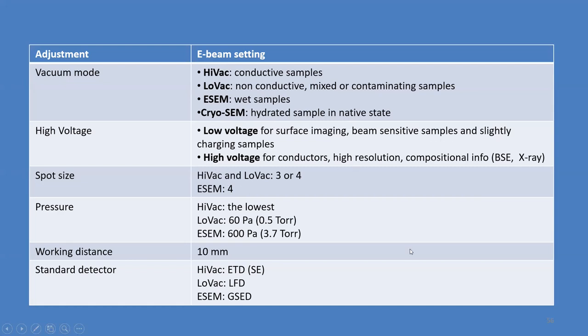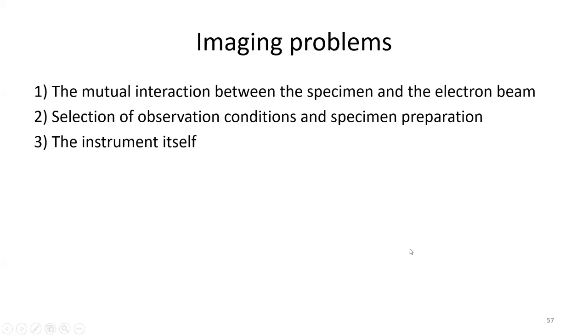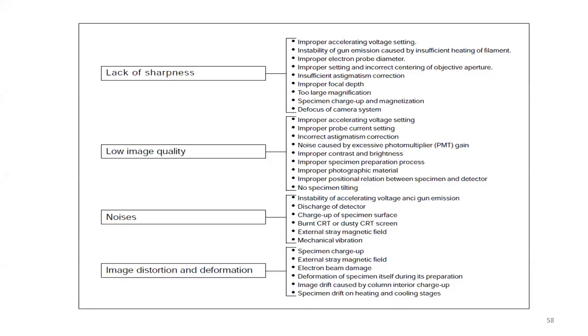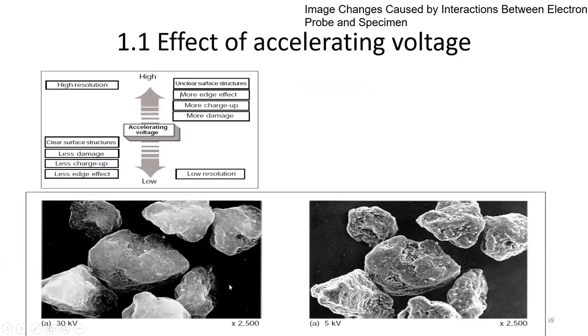Maybe I'll skip all the imaging problems. There are several problems that one comes across, like lack of sharpness, low image quality, noise, image distortion and deformation. For example, here is the effect of accelerating voltage. On the right-hand side at 5 kV, you can see much more detail of your specimen, whereas at 30 kV, the higher kV, you cannot see the surface features. You can get high resolution at higher kVs, but with very unclear surface features, more edge effect, and more problems.